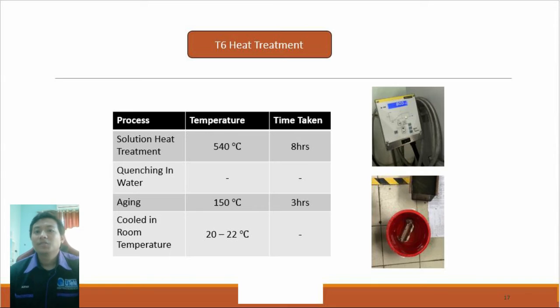This is the T6 heat treatment. This is the parameter for the T6 heat treatment. The process includes solution heat treatment, quenching in water, aging, and cooling at room temperature. The solution heat treatment is at 540 degrees Celsius, and the time taken is 8 hours. Quenching is in water at room temperature. Then aging, the temperature is 150 degrees Celsius for 3 hours, and cooling at room temperature between 20 and 22 degrees Celsius.